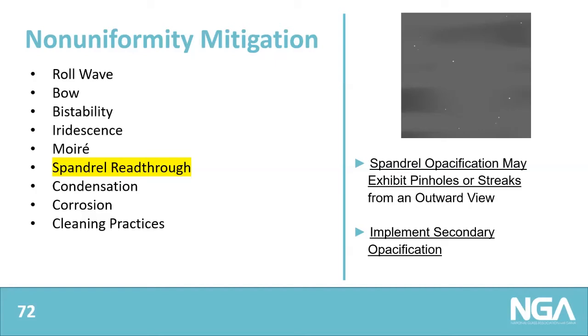So if you're looking at the spandrel glazing from the inside of the building, you could see pinholes or streaks. And again, this is not cause for rejection. The way that it should be addressed is with secondary opacification. So wall construction behind the spandrel glazing, so the occupants don't see these streaks or pinholes that are amplified by the intense sun shining through the glass.